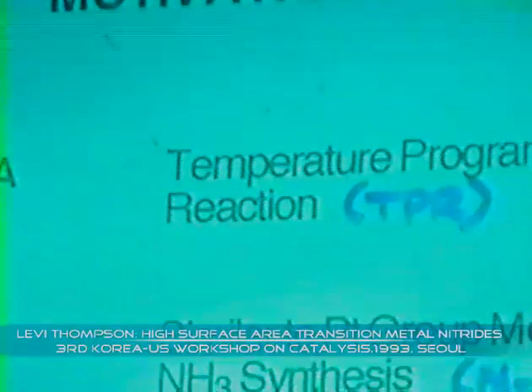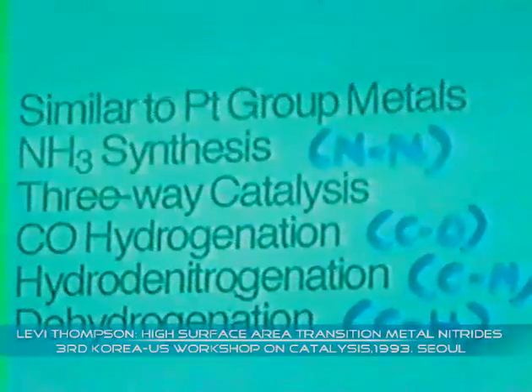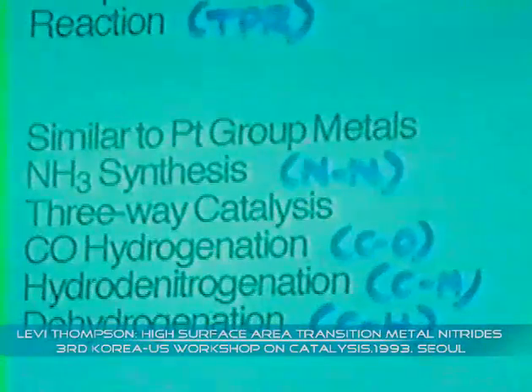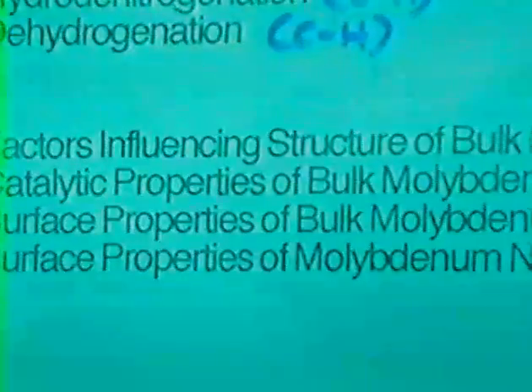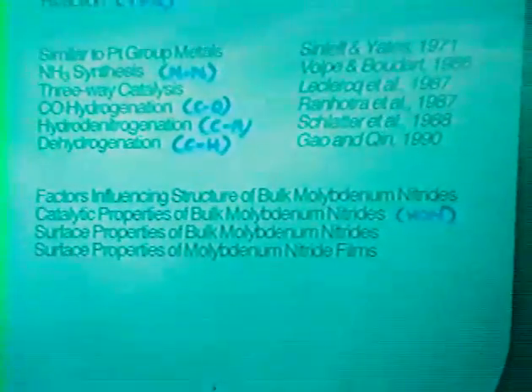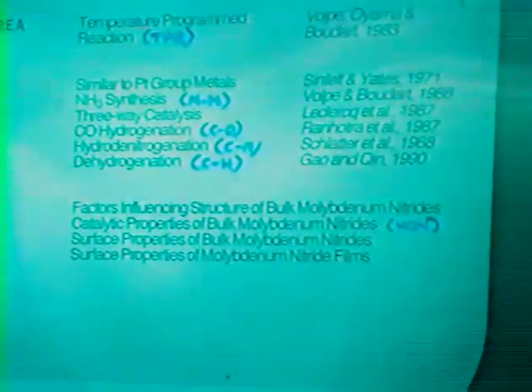Okay, the motivation for this work is basically twofold. Several years ago, maybe 10 years ago now, Boudart's group discovered that you could create high surface area, non-oxide materials using a technique called temperature programmed reaction. Basically, you heat a precursor, in this case an oxide precursor, in the presence of either ammonia or some carbonaceous species. And what happens is you convert that low surface area oxide into a very high surface area material.